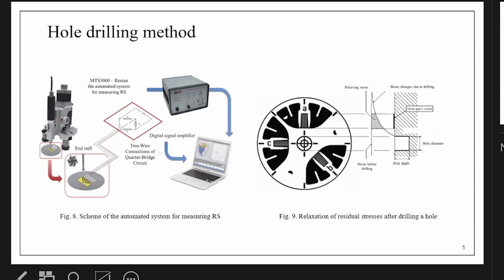Drilling is carried out step by step and at the end of each step, the value of the deformation arising from the removal of compressive residual stresses is recorded. Then based on the data obtained, we are solving the inverse problem and receiving profiles of compressive residual stresses. All measurements are performed in accordance with international standard ASTM E837.